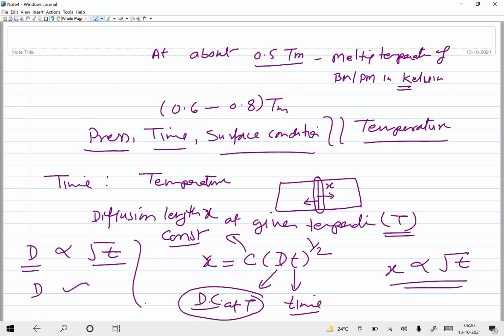Since the diffusion based reactions change exponentially with the diffusion bonding temperature, while they are affected as a square root of the time, there is a more significant effect of the diffusion bonding temperature as compared to the diffusion bonding time. So it is very crucial to control the diffusion bonding temperature, while the effect of the diffusion bonding time is somewhat less.